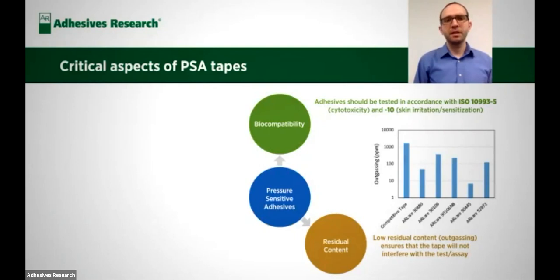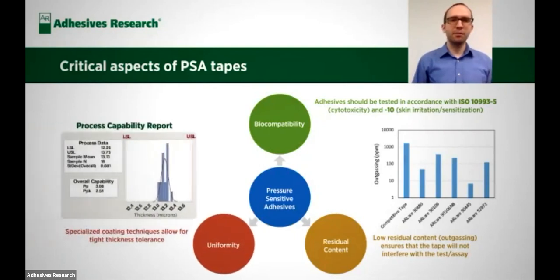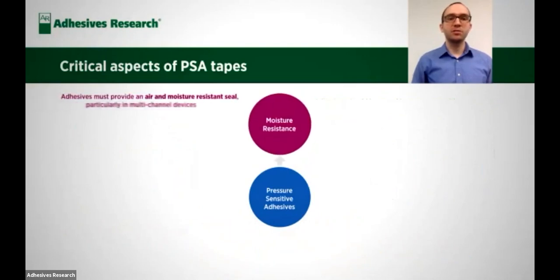drive down residuals. And in addition, the uniformity of the tape is very important, particularly for microfluidic devices. Your channel height is essentially defined by the thickness of your tape. So specialized coating equipment is needed to get very uniform thickness of adhesives for this type of application, and repeatable adhesive thickness as well. Another important aspect to consider is moisture resistance. Adhesives should provide a moisture or fluid resistant barrier. Particularly, this is important in multi-channel devices where you do not want fluids to be interchanging between the multiple channels of the device. That also includes, you don't want air or other contaminants from getting inside as well.